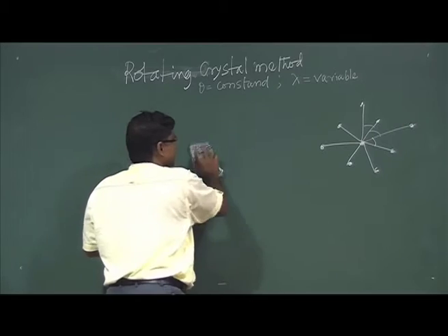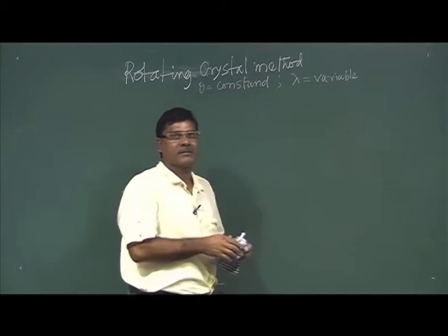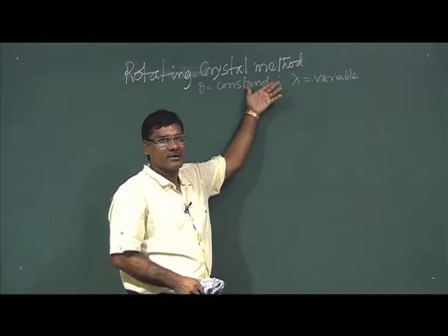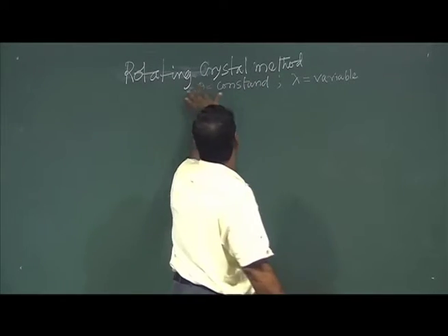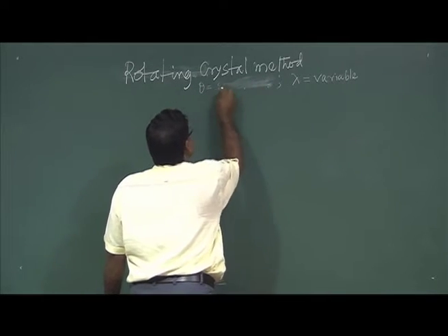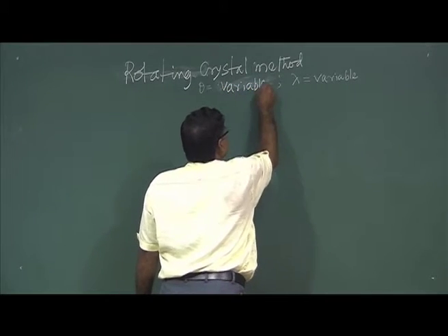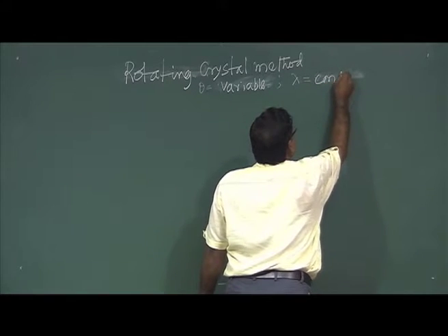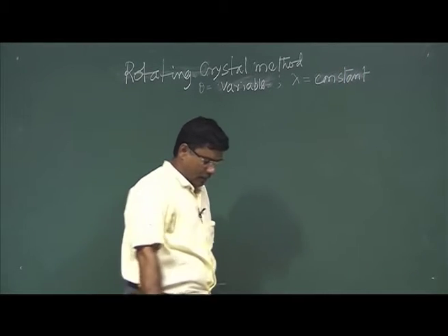But the diffraction pattern we get depends on the method, and the method depends on the experimental geometry. In this method, theta is variable and lambda is constant, meaning monochromatic X-ray will be used.